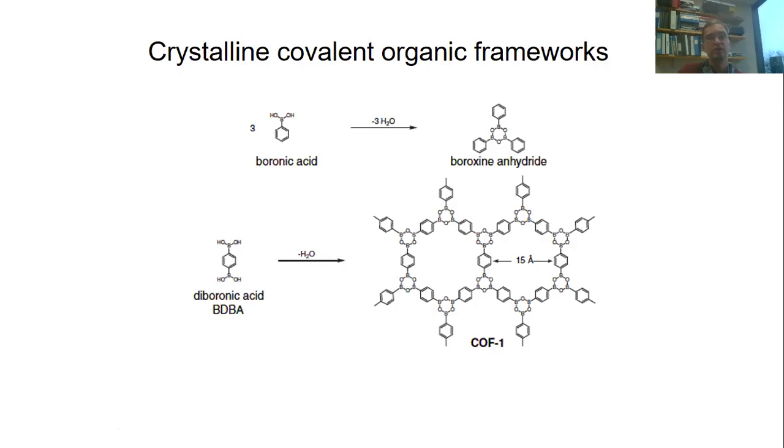And if it meets another molecule while it's out of plane, the two building units will connect incorrectly. If that bond formation was irreversible, we would probably arrive at an amorphous product, because the reaction would be kinetically controlled. That means that whatever forms first will eventually also be the final product, which is not necessarily the energy minimized structure.